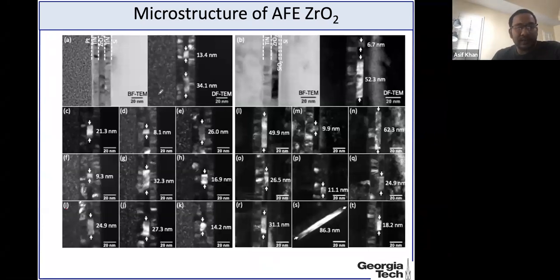Then we also did dark field TEM imaging to find out the grain size distribution. A common limitation that people usually mention is that it's not representative. So we analyzed around 200 DFTEM images to get a grain size distribution. We saw that within 10 nanometer films, the smallest grain size, I believe, is around 4 nanometers, and the largest was above 90 nanometers. One of the small ones I don't see here, but I remember seeing one of the 4 nanometer size grains.